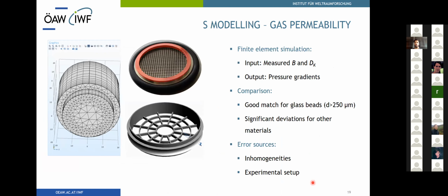To verify the gas flow measurements, we decided to implement the gas flow model in a finite element simulation. The approach was to use the flow parameters determined from the measurements as an input in the simulations and compare whether the resulting pressure gradients would match that of the experiment. A good agreement was found for the glass bead samples down to a diameter range of 250 micrometers. The smaller beads and all other materials, however, showed significant deviations. The most probable source for these discrepancies is the irregular grain shape, due to the reasons explained before.